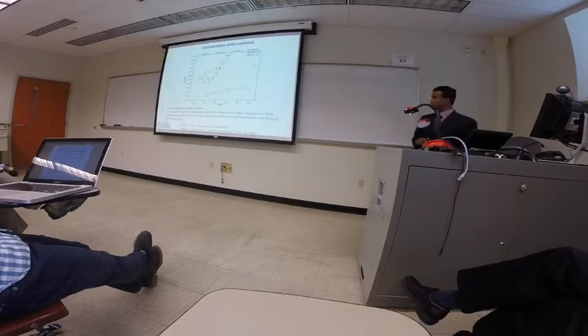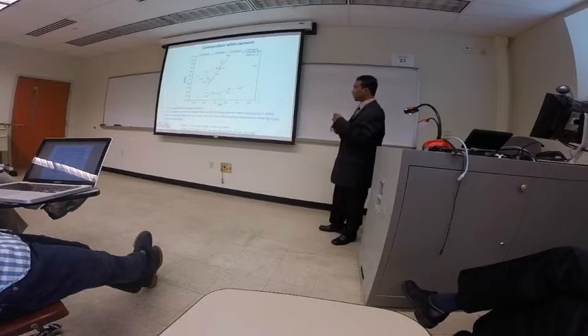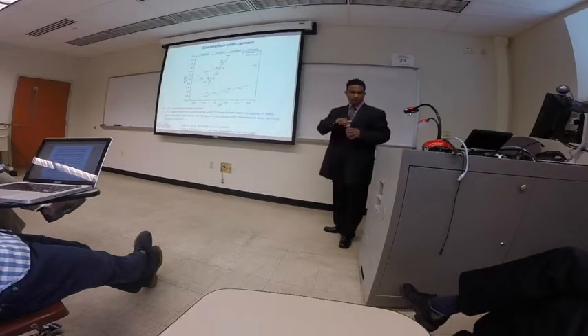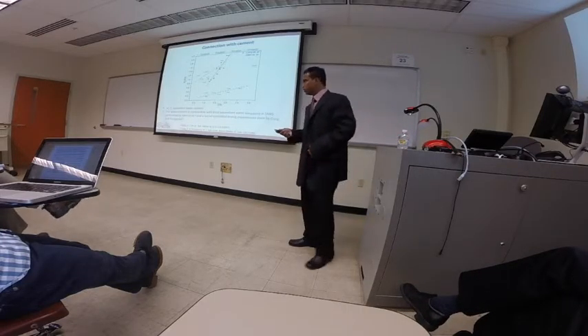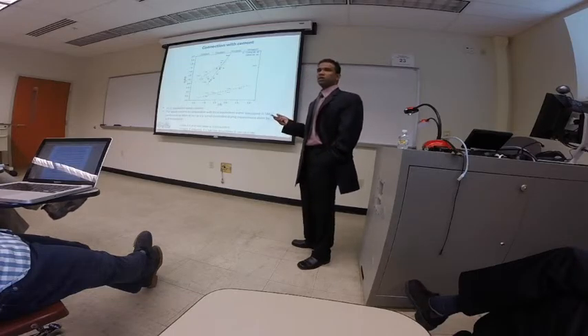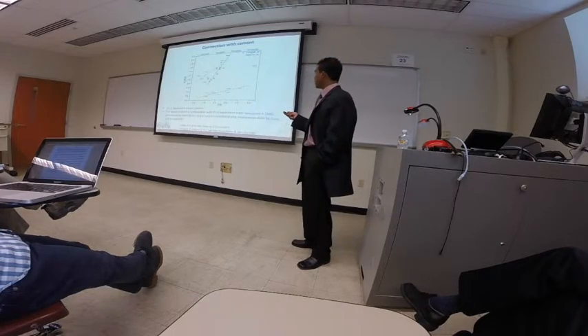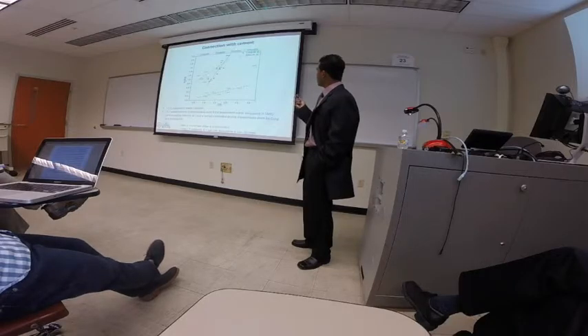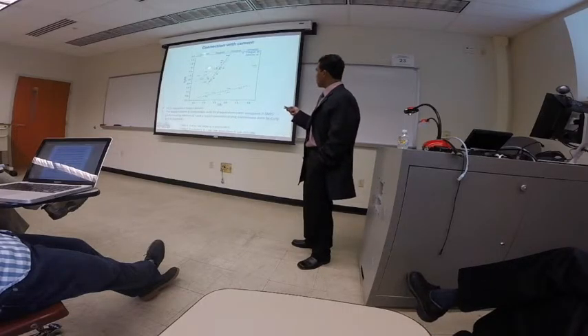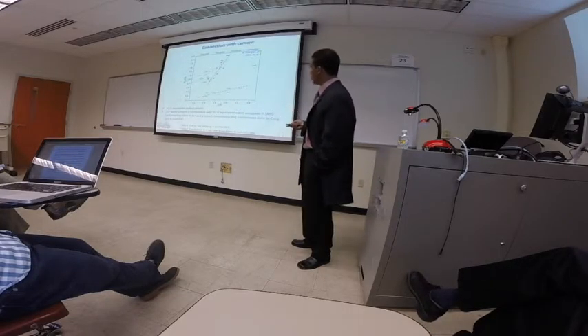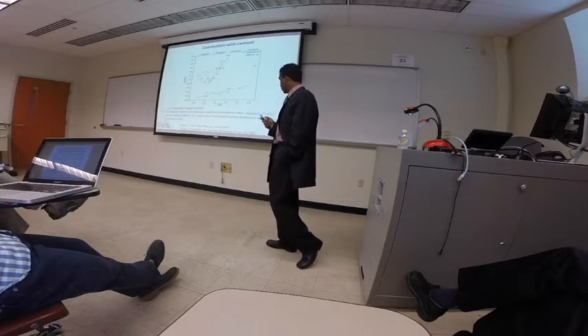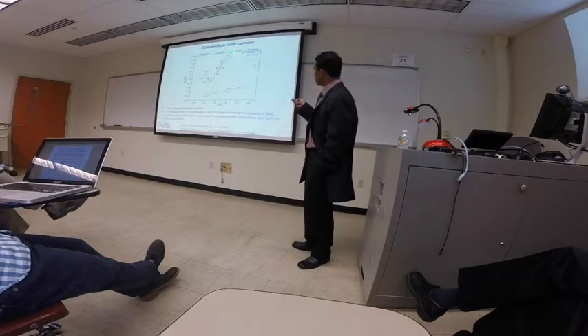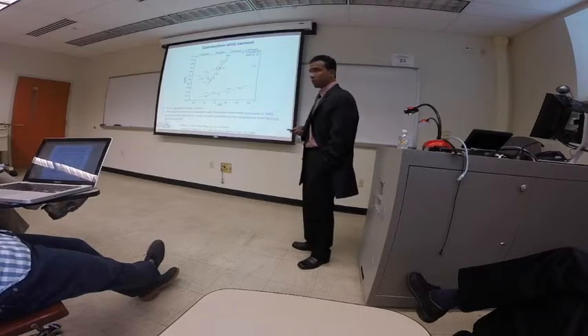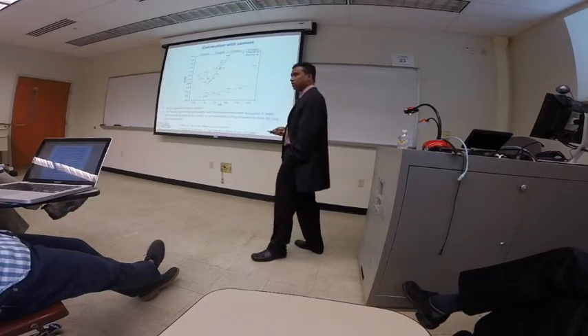So to put these 20 crystals in perspective, would it make sense to use 20 crystals? Would it tell anything about cement at all? We compared it with two experimental studies done for synthetic cement, not crystals, where they tried to find a correlation between water to silicon ratio against C/S ratio, and they found this trend. So we thought we should put our crystals in the same diagram to see if there's any correlation.